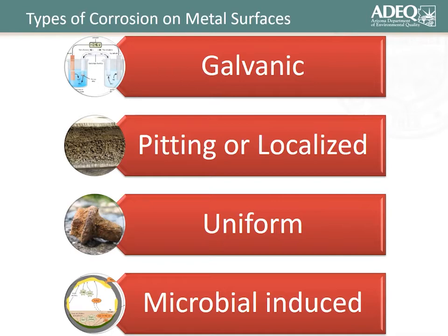And more recently, we're spending more time understanding how microbially induced corrosion could be impacting a water system. Bacteria give up enzymes. Enzymes end up being acidic. So the acidic nature of enzymes emitted from bacteria ends up touching these metal surfaces and touching these lead scales, and therefore causing release of these metals. So it's a lot of investigative work when it comes to a water system exceeding their lead or copper action level.